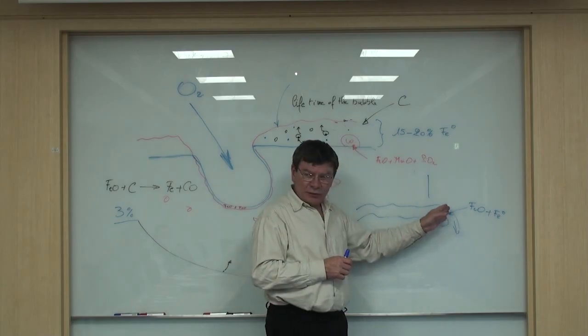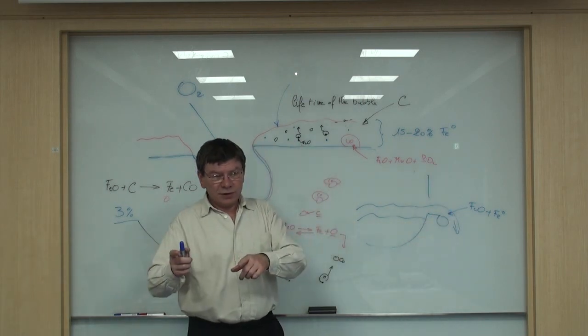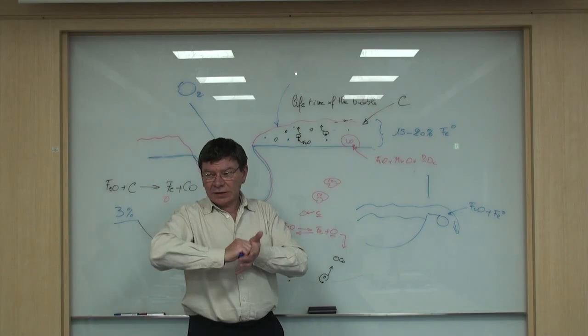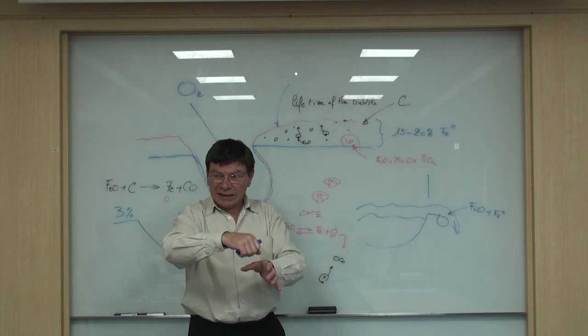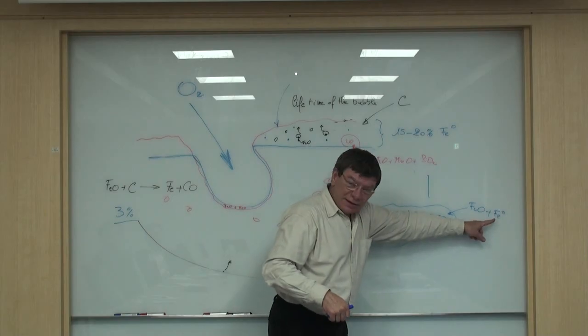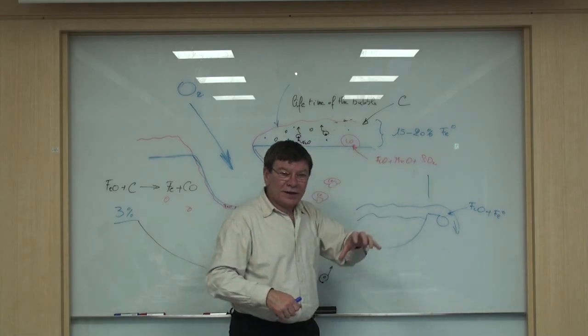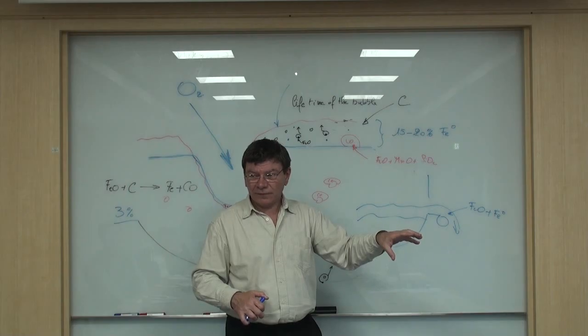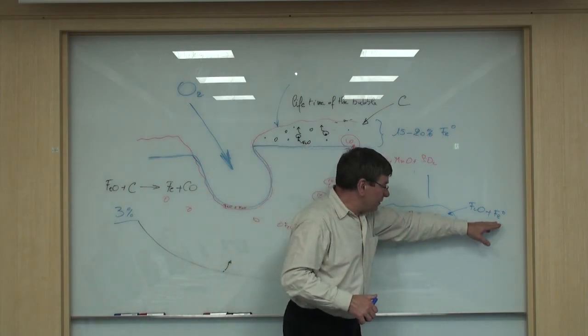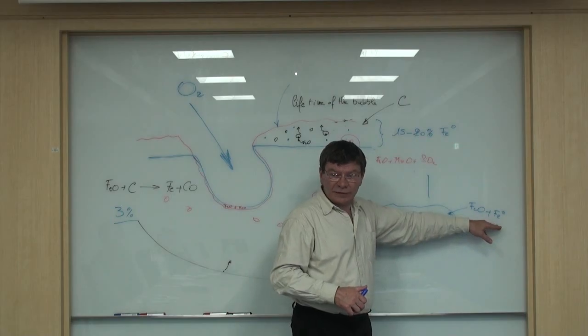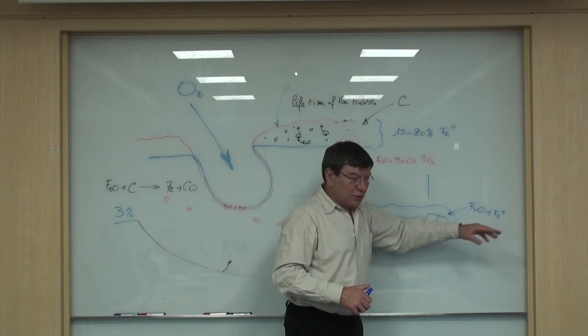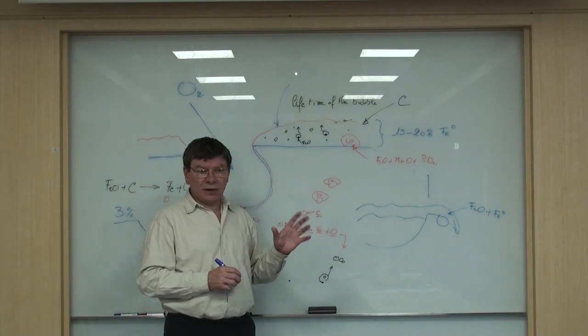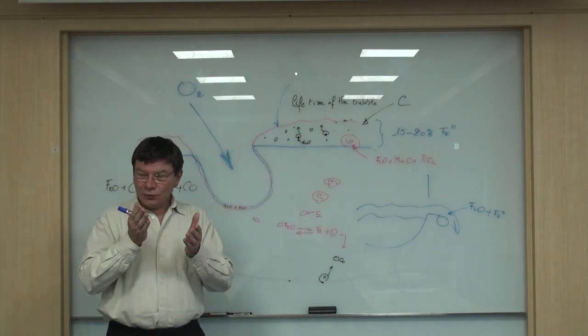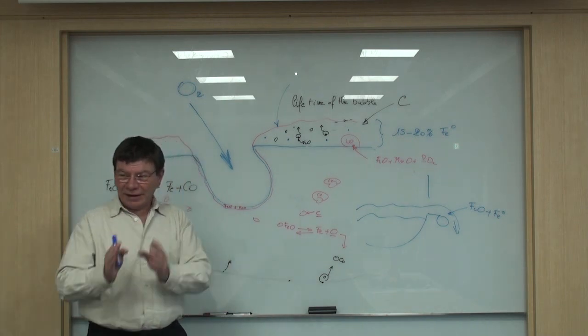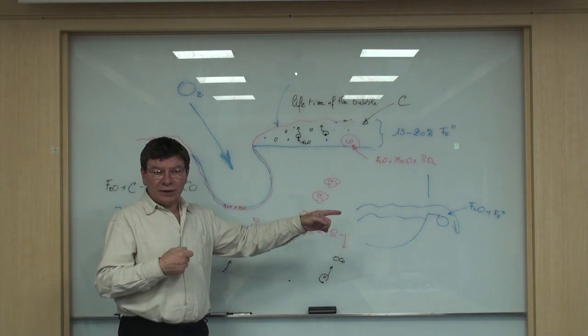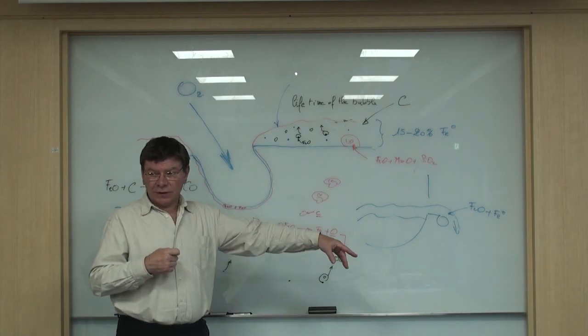Secondly, when they take the sample, usually they go to the lab and the lab crushes the slag, removes the magnetic particles, and then analyzes what is remaining. So they are just ignoring the metallic Fe. In the past, I was asking the lab to crush and weigh the non-magnetic and the magnetic parts to have an idea of how much metallic iron is getting out of the furnace.